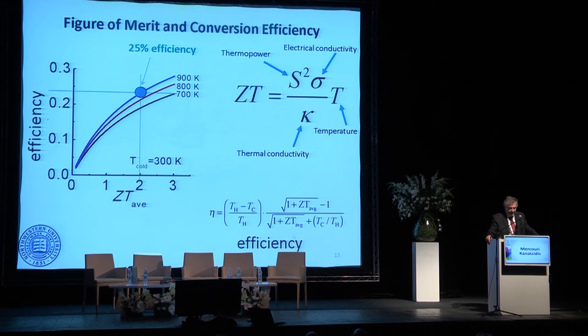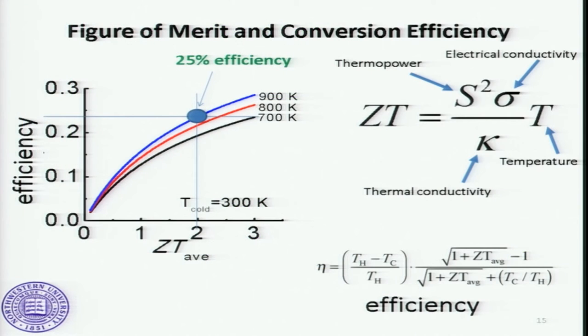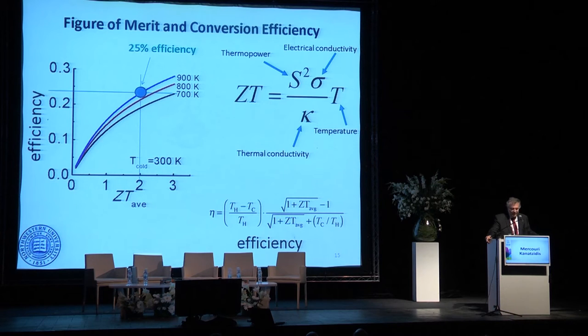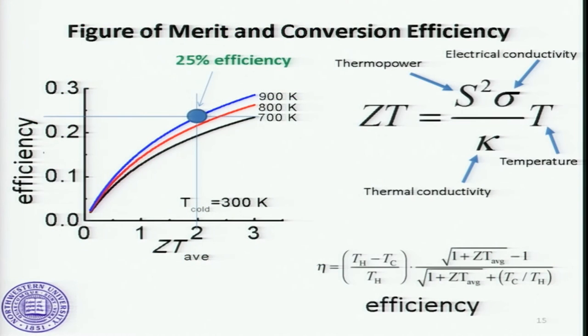So, thermoelectric power is the key property, but it's not the only property. S is the thermoelectric power. The way you can tell a material, a semiconductor, is any good is by this ZT value. The material has to have a very high S, so it goes by the square of that, that's good, but it also has to have high electrical conductivity, that's the sigma, and very low thermal conductivity, and that's the K. So you need to do something to the material to maximize this fraction. You need to minimize the thermal conductivity, for example, without hurting the other properties. The problem is these properties are interrelated, and sometimes when you raise one, you decrease the other. They fight against one another. And that's what makes this so difficult.